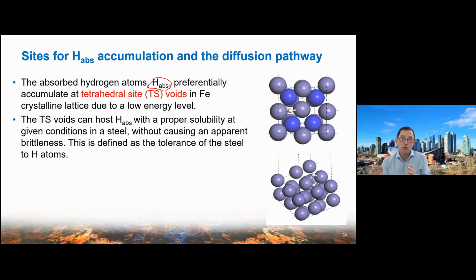It tends to be located in the tetrahedral sites, because everybody knows steel is mainly composed of Fe atoms. Fe atoms are put together and form space between them. This space we typically call a void. The hydrogen ABS will be located in the tetrahedral sites, surrounded by 4 iron atoms, not 8, based on the different energy levels. We have the detailed calculation of the energy, but I do not talk too much about the calculation.